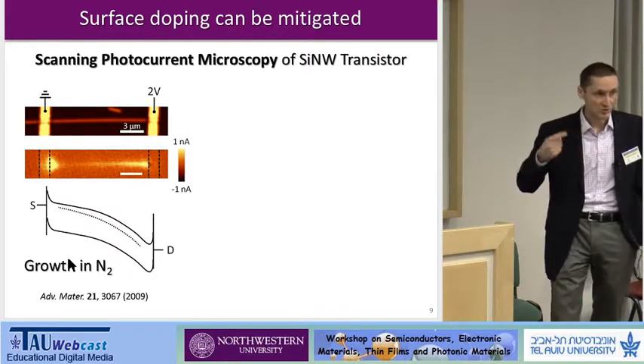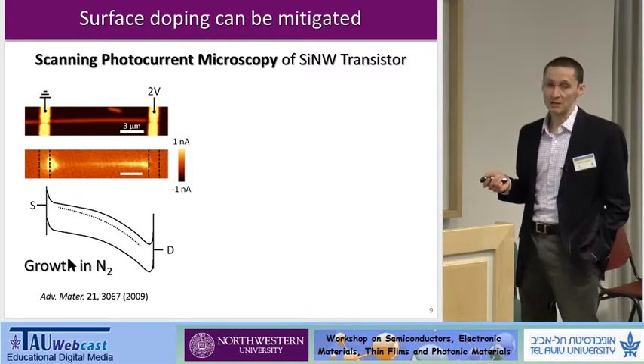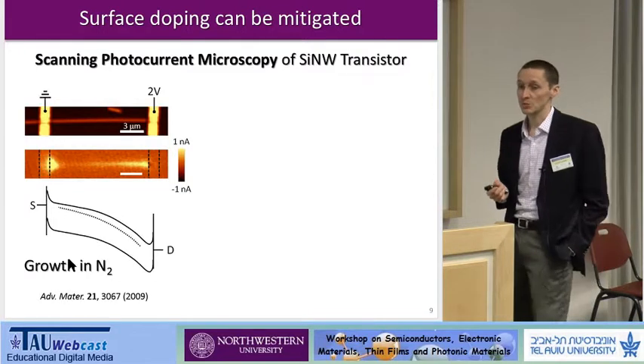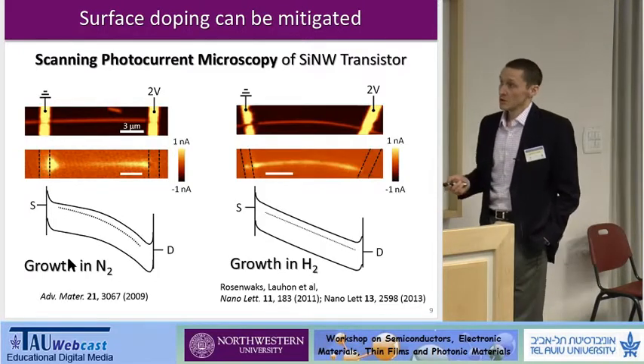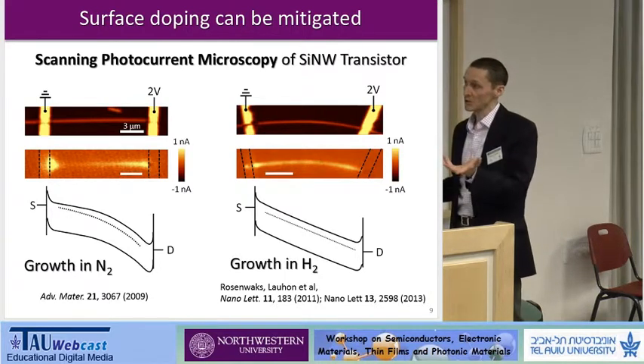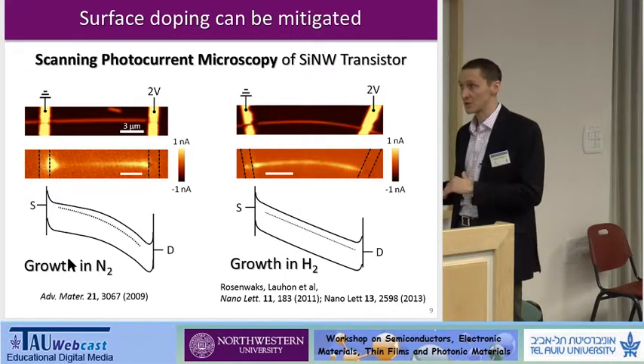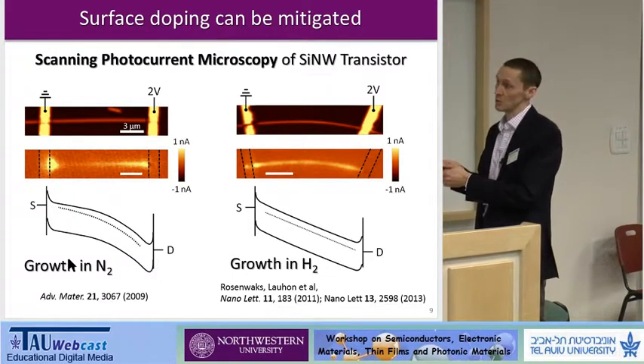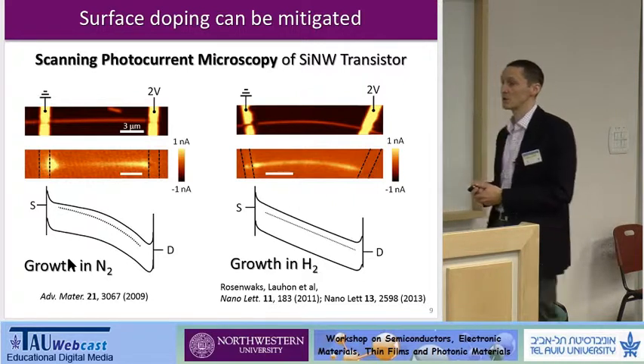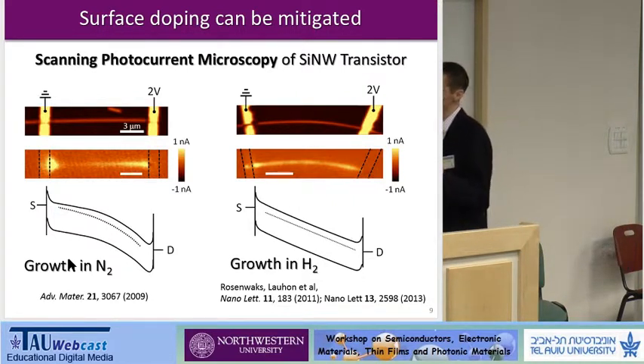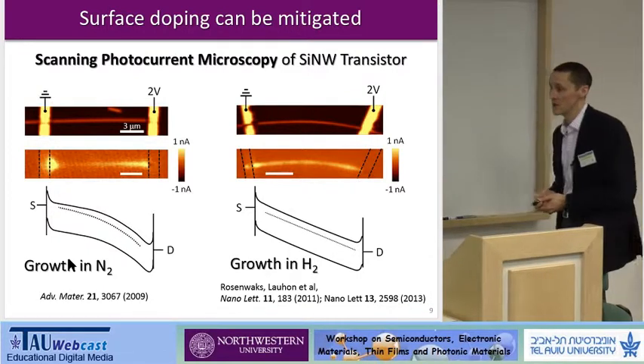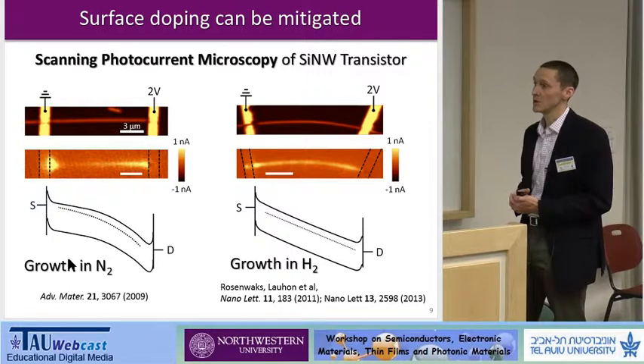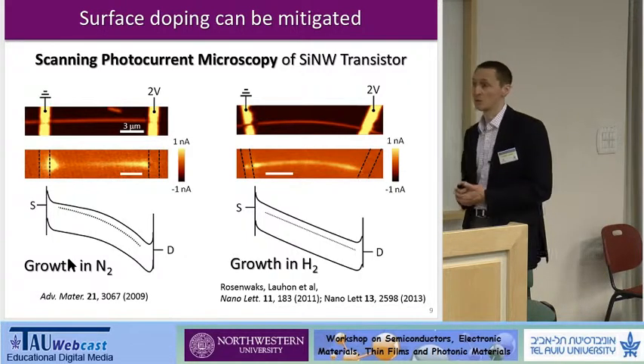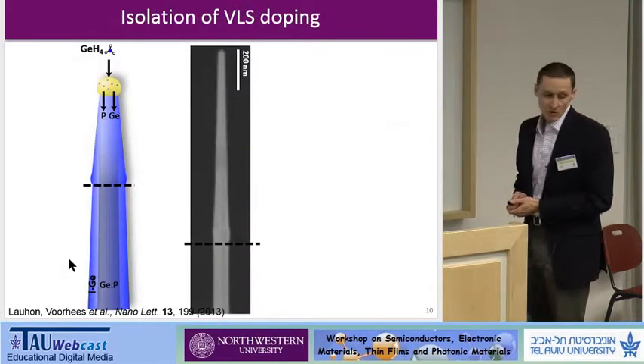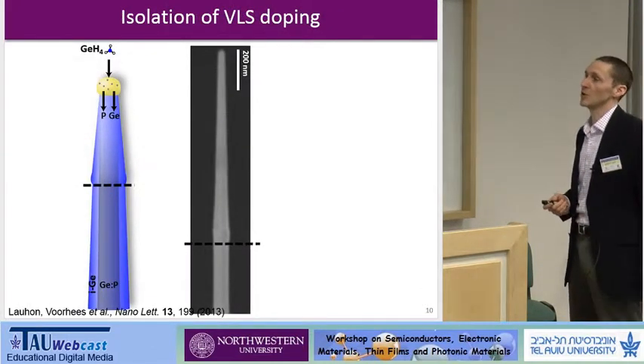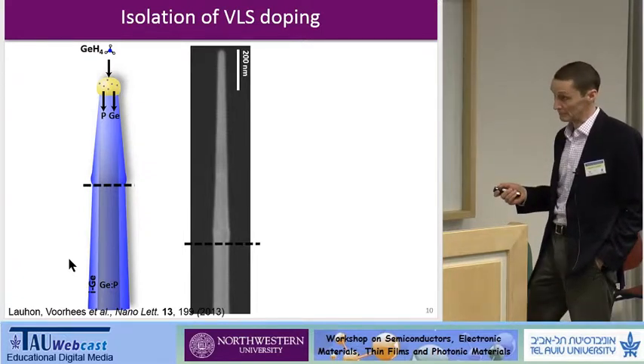So this is, in essence, an image of this surface doping process that can be made even more quantitative by combining these SPCM measurements with Kelvin probe measurements, as we did with Yossi. So with this additional understanding of inactive versus active dopants, we could tailor the synthesis conditions and produce, in this case, a more uniform response in the device channel, a linear potential drop across the material. And again, in this case, feedback synthesis, the device properties back into the synthesis conditions. And so these are a couple papers that, again, we worked on with Yossi, essentially explaining what was going on in this context. So as we were studying this dopant, I would say the studies were not without their surprises.